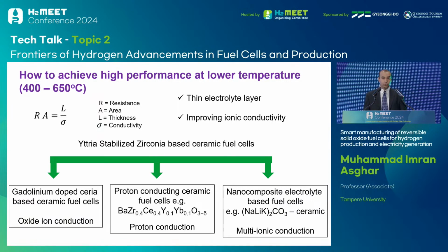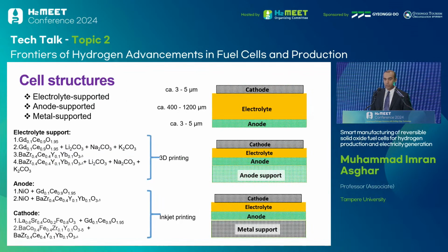There are three approaches to do that. One approach is to decrease the thickness of your electrolyte. The other approach is to improve the ionic conductivity of your electrolyte materials. There are three ways to improve the ionic conductivity. One way is to use gadolinium-doped ceria-based materials. The second approach is to use proton-conducting materials. And the third approach is to use composite electrolytes. So these are three ways to improve the electrolytes.